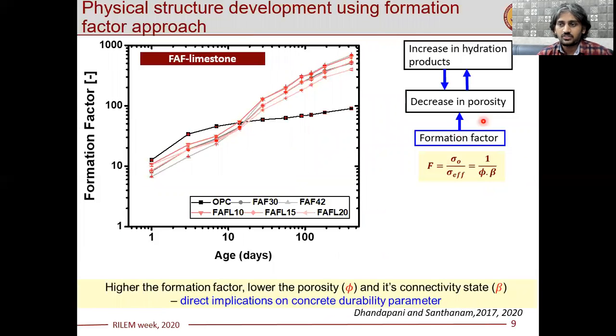We try to address this using the formation factor approach, which gives an indication of both porosity and pore connectivity by taking the relative conductivity of the pore solution and the bulk conductivity of the system.